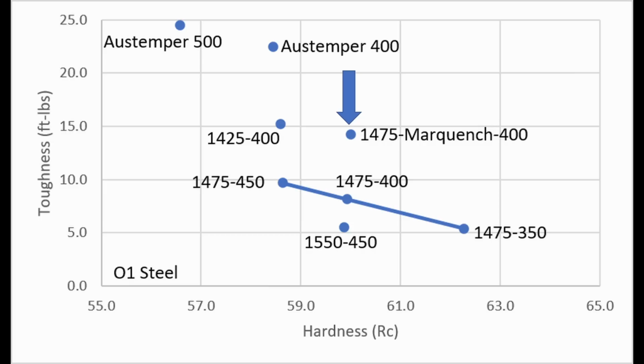It was similar toughness to our 1425 austenitize, even though we austenitized at 1475. Also, the hardness was identical to my conventionally quenched in oil O1 from 1475 and tempered at the same temperature of 400 degrees. When I austempered at 400, so full bainite, I got 59 Rockwell, a little bit under the 60 Rockwell the TTT diagram said, but in the same ballpark, and the toughness was significantly increased over the mar quench. When I austempered at 500, I got 56.5 Rockwell, close to the 56 Rockwell that the TTT diagram claimed, and a little bit higher toughness than the 400 degree austemper. But just like the 52100, I would probably prefer the lower austempering temperature, get an extra Rockwell or two with only a small cost in toughness.